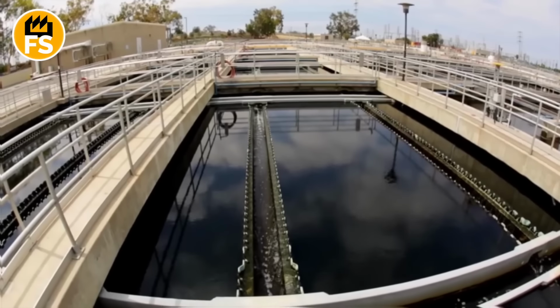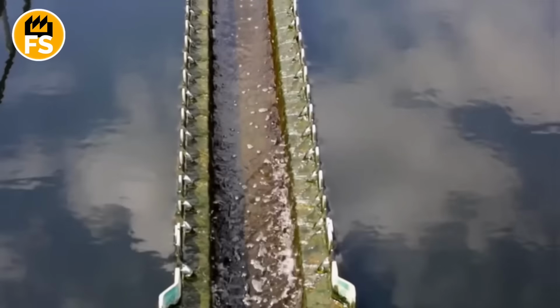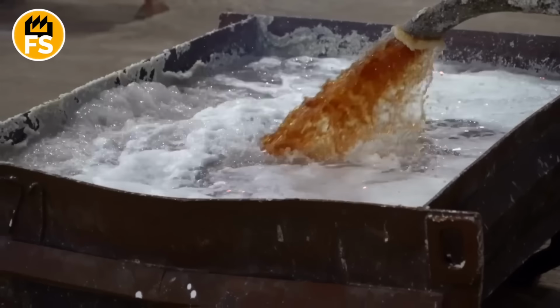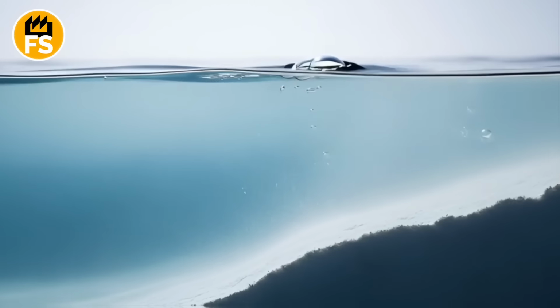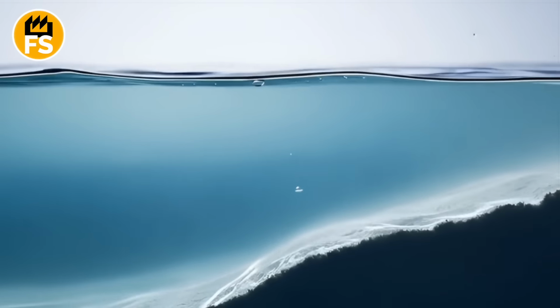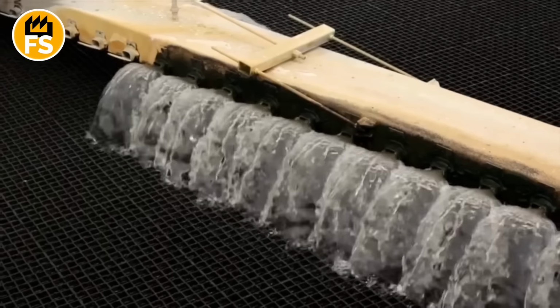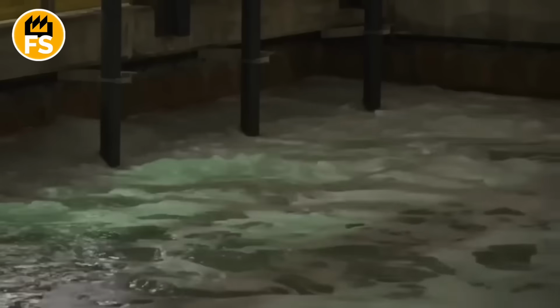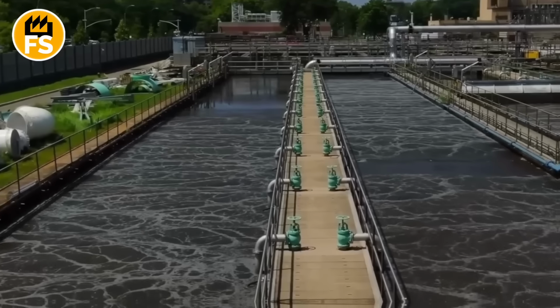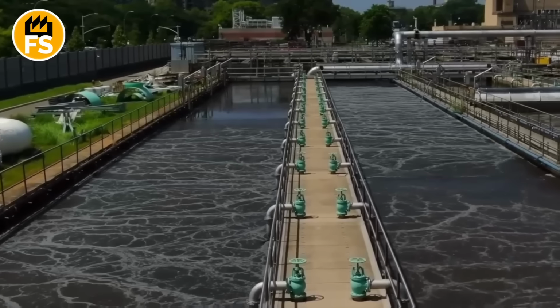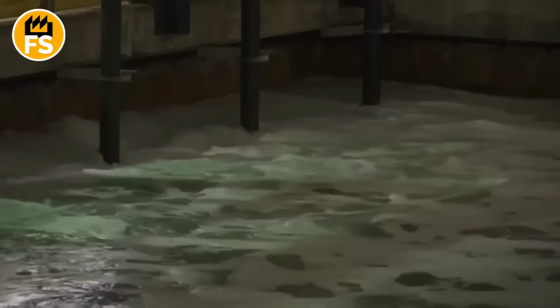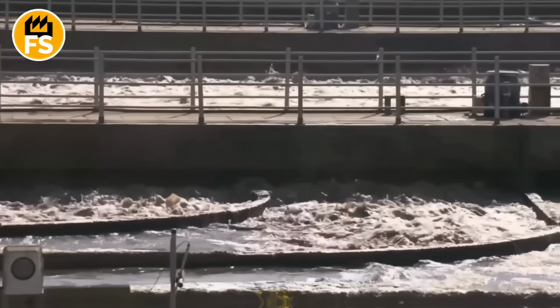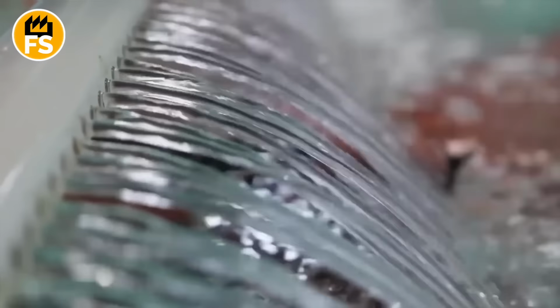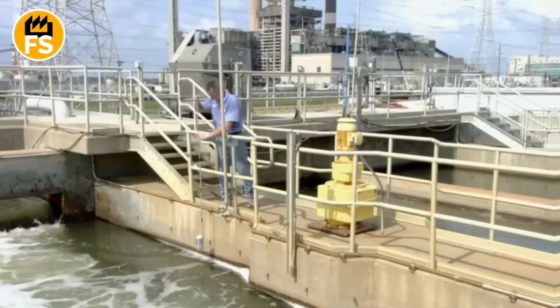From the outside, it looks like a slow transformation of transparent seawater into a cloudy liquid, as if someone added fine white powder that gradually binds the dissolved magnesium into flakes of sediment. While the reaction continues, large mixers move through the pool, sometimes resembling windmill blades, only turned horizontally. They stir the liquid almost silently, so the sediment forms everywhere rather than clumping together in one spot. When the particles become heavier and start settling to the bottom, the liquid is pumped into the next settling tank.